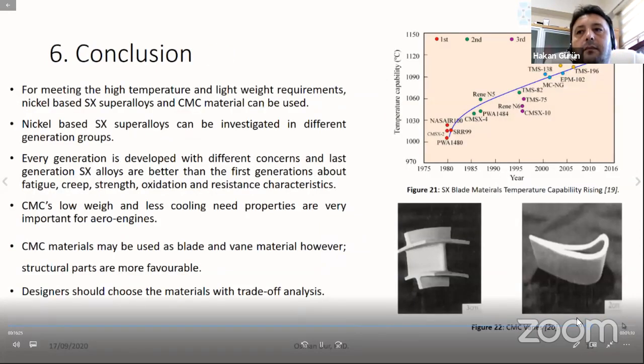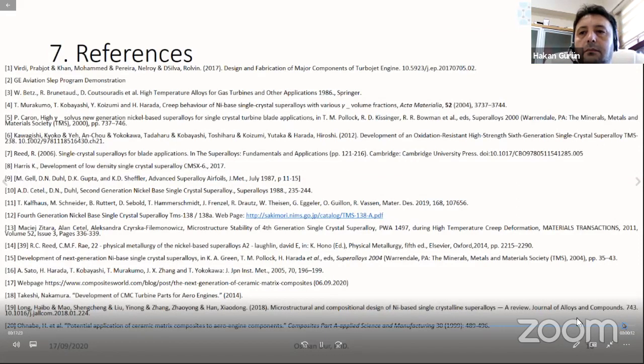As a result, for meeting the high temperature and lightweight requirements, nickel-based superalloys and CMC materials can be used. Nickel-based superalloys can be investigated in different generation groups. Every generation is developed with different concerns, and last generation alloys are better than the first generations for fatigue, creep, strength, oxidation, and resistance characteristics. CMC's low weight and less cooling need are very important for aero engines. CMC materials may be used as blade and vane materials. However, structural parts are more favorable. Designers should choose the materials with trade-off analysis. Now, these are the references. Thank you very much.